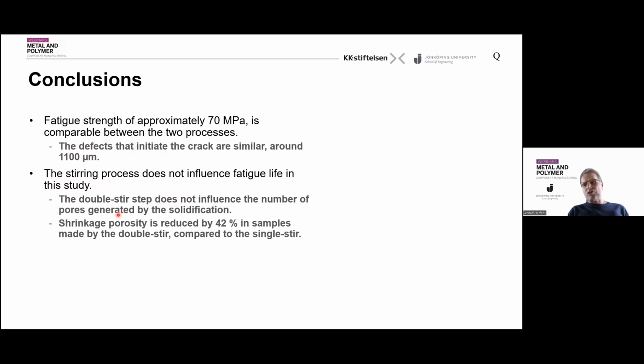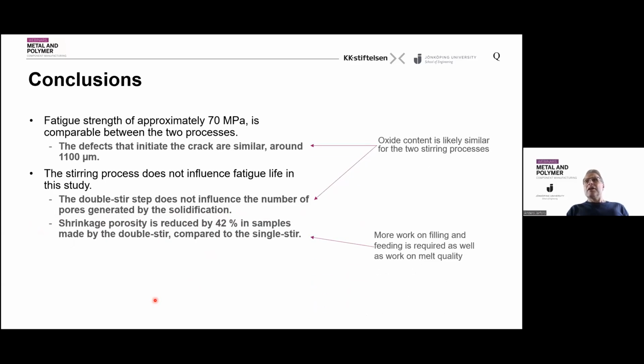So that means that we did not really introduce more defects by stirring a second time. But the issue is still that even though shrinkage was significantly reduced, we did not strongly affect the fatigue life. So what we saw here is that the oxide content is probably similar for the two processes, but we need to work more on how to actually manage filling and such.